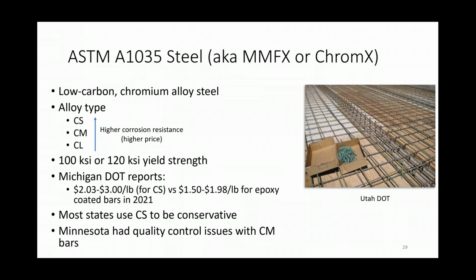So most states use the CS type because that's supposed to provide the most corrosion resistance. And Minnesota reported some quality control issues with the CM type. So the manufacturer is aware and working on that. The cost is a little bit higher. I put the Michigan DOT numbers here, so $2 to $3 a pound versus $1.5 to $2 a pound for epoxy coated bars.